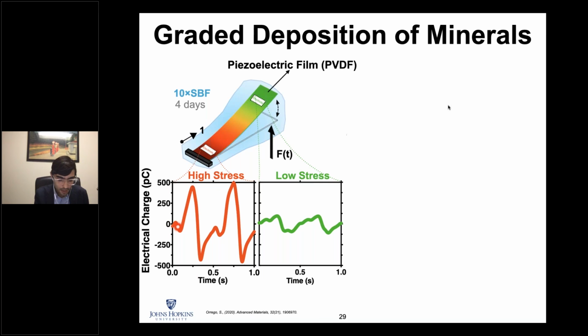As measured here, these regions of high stress have a high amount of charges, between minus 500 to 500. In regions away from there, they have lower charges, between -100 and 100.